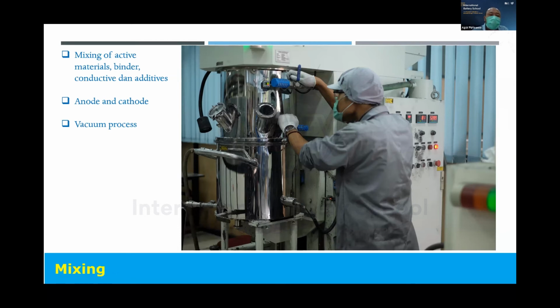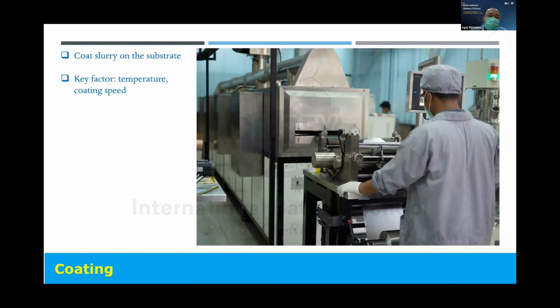Here, the mixing process is used for anode and also cathode, and the important thing in the mixing process is using vacuum to ensure there is no bubble inside the slurry, because if there is a bubble inside the slurry, the film will not have good density, and maybe affect the morphology of the film. Then after the slurry is ready from the mixing process, we move to the coating process.